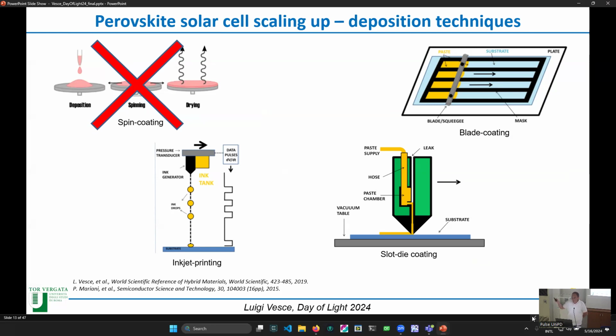You have this bar that deposits the material on the substrate, and you have to control the meniscus, that is the gap between the lip and the substrate. The slot die has a similar working mechanism, but the only difference is that you have a continuous supply of material inside the head coater. This is good for very big substrates.